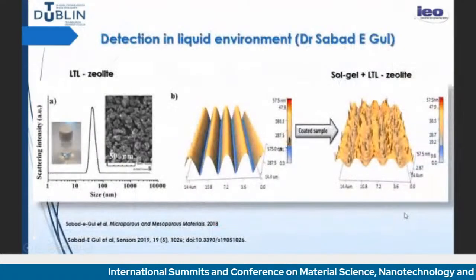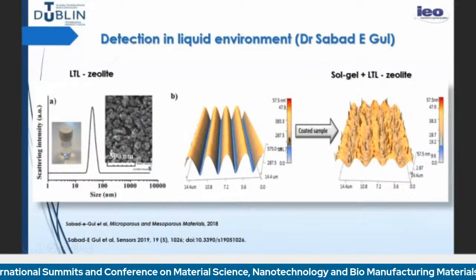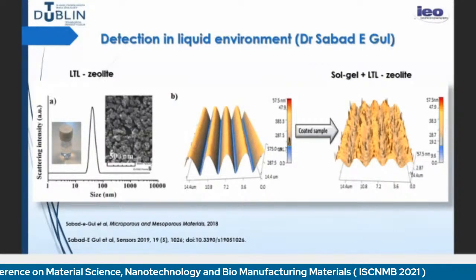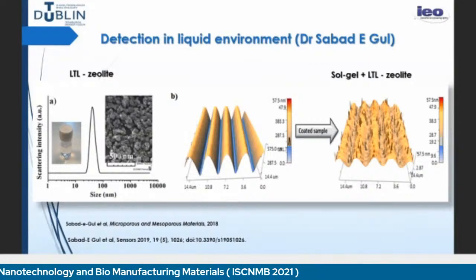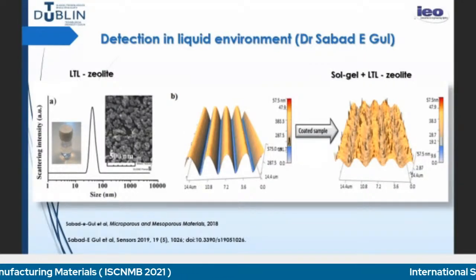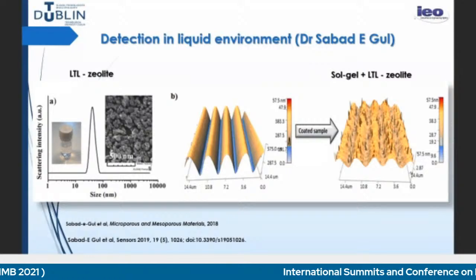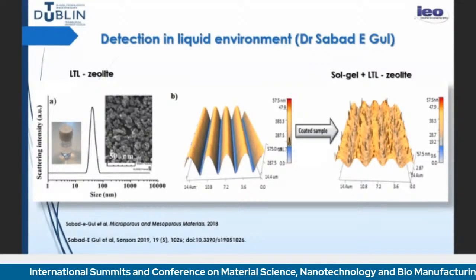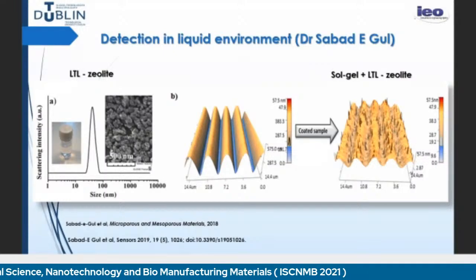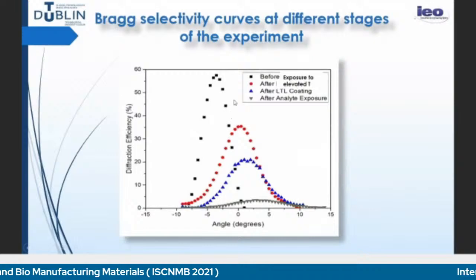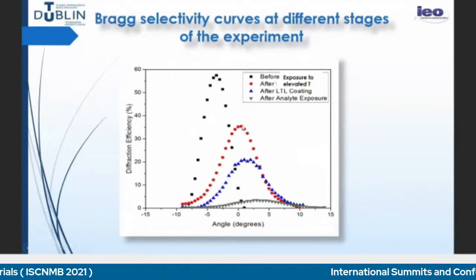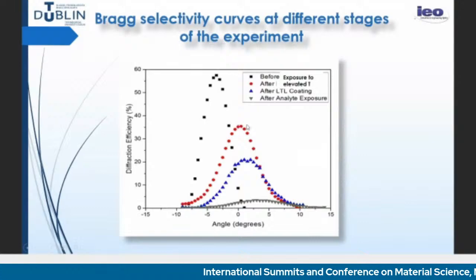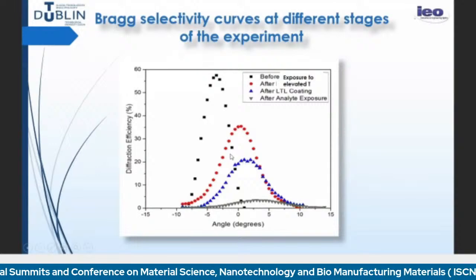So in terms of detection of metal cations, this is work of Dr. Sabad E Gul, who is now a postdoc in Canada. She coated the surface gratings with zeolites, but zeolites in sol-gel materials, because just zeolites, they washed away in water. And the change in diffraction efficiency is not due to the absorption of the analyte. So for that reason, we had to develop a sol-gel plus LTL zeolite material and coat the structure. And this is the grating initially recorded. Then we treated at very high temperature, 220 degrees, to obtain a surface structure which is not dissolved in water, absolutely stable over time. And we coated with the zeolite in sol-gel.